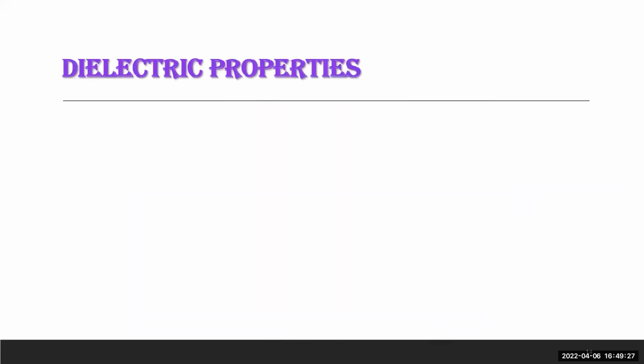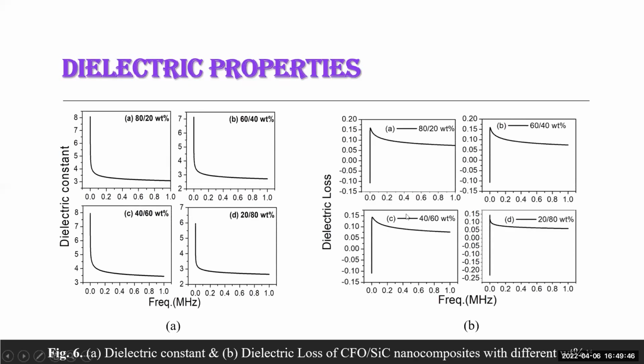Then moving towards our next property, that is the dielectric property. Dielectric measurements, including frequency dependence of capacitance, dielectric constant, and loss, were recorded using an LCR meter in the frequency range of 20 Hz to 1 MHz at room temperature for the cobalt ferrite, silicon carbide, epoxy nanocomposite. So this is the figure. Figure A shows the variation of dielectric constant with frequency, and figure B shows the dielectric loss with the variation of frequency.